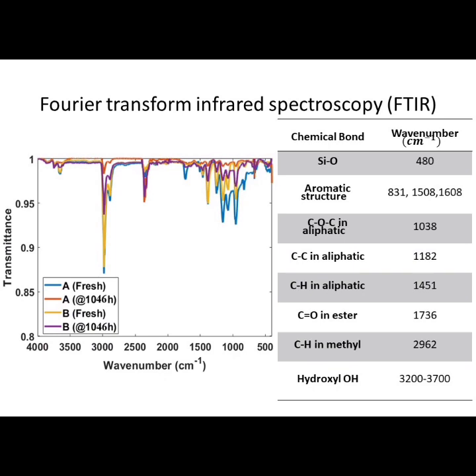Also, the epoxy resin in sample A, the normal FRP rod, was found to be more severely degraded, as the corresponding peaks of methyl, aromatic structure and also aliphatic groups were drastically reduced compared with the tracking resistant FRP rod. In addition, there is an obvious reduction in the transmittance peak corresponding to the Si-O bond in the glass fiber, which indicates a severe hydrolysis and ion exchange of the glass fiber in sample A compared with sample B. Finally, the absence of the spectrum peak corresponding to the ester group in sample B is due to the absence of the coupling and curing agent.